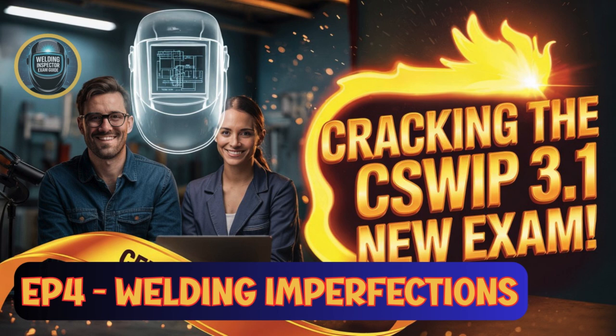Okay. Finally, within cavities, we have crater pipe. Definitely heard that term. It's that little dip or hole you sometimes see right at the very end of a weld run, correct? Yeah, that's the one. It's a shrinkage cavity that forms right at the conclusion of a weld run, where the weld pool solidifies last. It's commonly caused by, frankly, a lack of welder skill, particularly when using processes with maybe too high a current for the stop. Right. In TIG welding, it can also be due to an inoperative crater filler or slope-out function on the machine. To properly fill the crater in TIG and prevent that pipe, you need to gradually reduce the weld current in descending steps until the arc extinguishes. It's a specific technique called slope-out, and it's crucial. Got it.